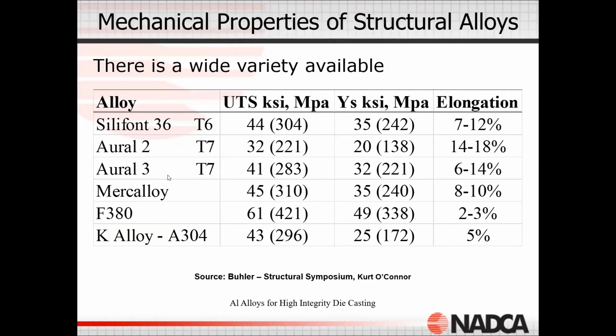This is just an example of these alloys and their tensile, yield, and elongation. And I just want to point out that elongation levels on some of these alloys can reach as high as 18% and not see a reduction in tensile or yield, or a dramatic reduction. Some of these alloys can be made so that they have very high tensile and yield and low elongation. So we're approaching iron forgings as far as the ability for tensile and yield of these type of alloys.